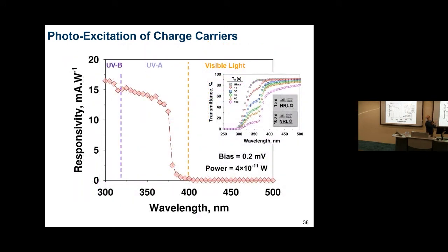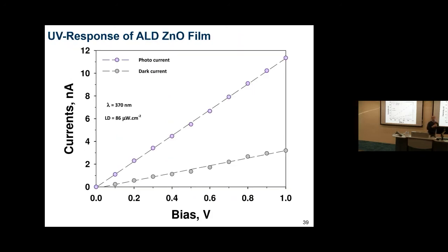We have found a way also to tune this as a function of the material composition. If you would do the same with a zinc oxide film deposited by ALD, for example, the change in photocurrent is not order of magnitude - it's a very small change.